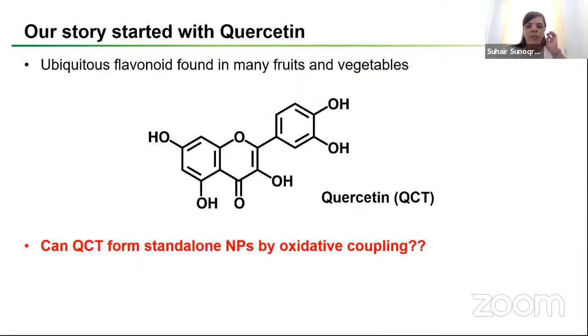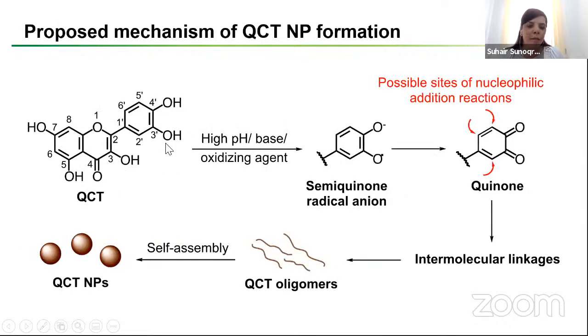So in our case, we looked at quercetin because we were already working with it as a therapeutic agent. We had it available in the lab. So we wanted to see if this structure can actually form nanoparticles with a similar mechanism. The proposed mechanism was that when these adjacent catechol OH groups undergo oxidation, whether at high pH or in the presence of a base or an oxidizing agent, the ring becomes reactive. And if you have a nucleophile in the reaction vessel, it can attack the ring, resulting in a cascade of reactions that lead to the formation of these oligomers, and then they can maybe self-assemble into nanoparticles.